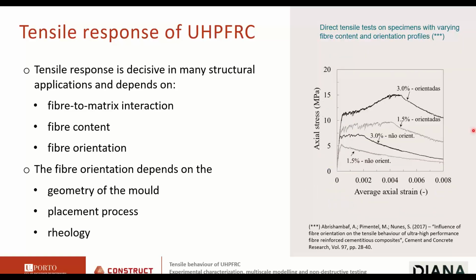And here, another interesting result. This is the same UHPFRC mix that I described at the beginning of this presentation. We can see that the black curves correspond to specimens with 3% of fibers and the light gray to 1.5% of fibers, so half the fiber content. What do we see? If we orient the fibers properly, we can have a better tensile behavior than what we would obtain with twice the fiber amount, but with the fibers not oriented. So the orientation of the fibers can have an effect that is even more important than the fiber content.